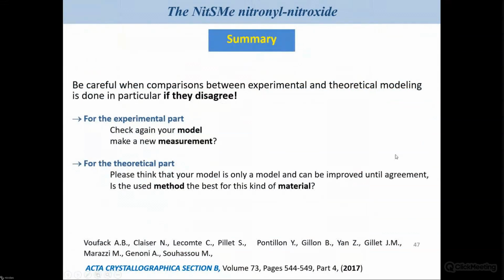So what can we conclude from that is, in such a kind of system for which the effects are very tiny, you have very, very small interactions that appear at very low temperature, it's really important to have a convergence between your calculation and your experiment. So if this is not the case, you have to check all the experimental parts, all the theoretical parts, to be sure that at the end you will have a convergence.